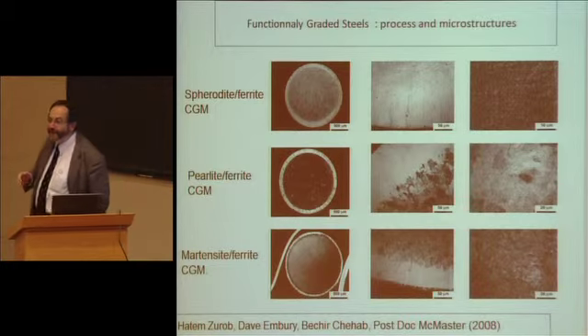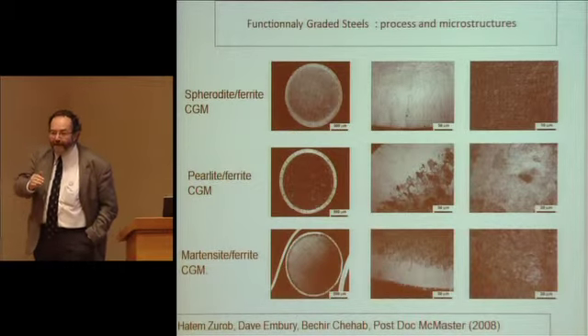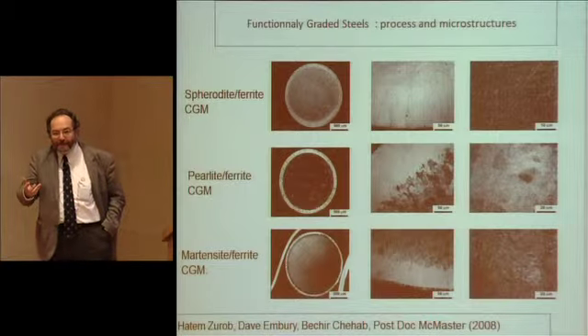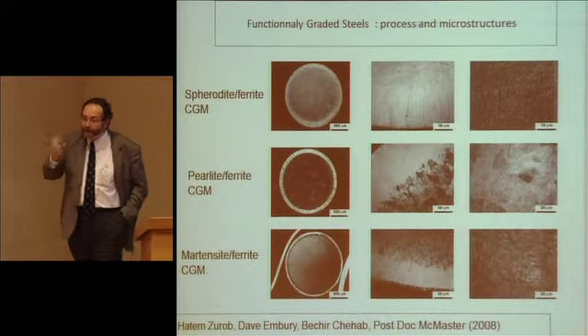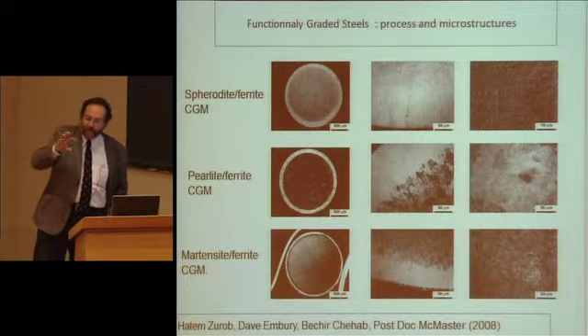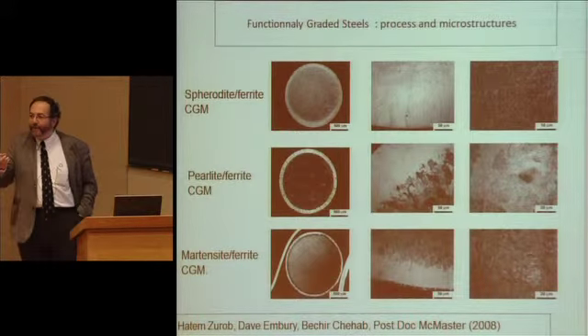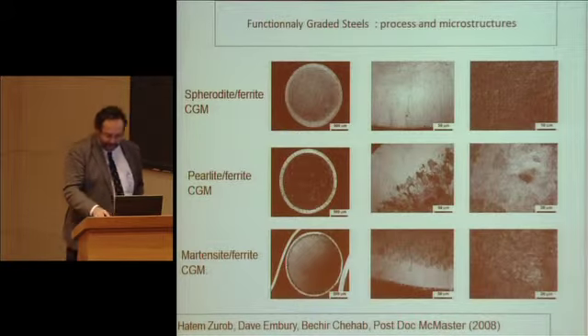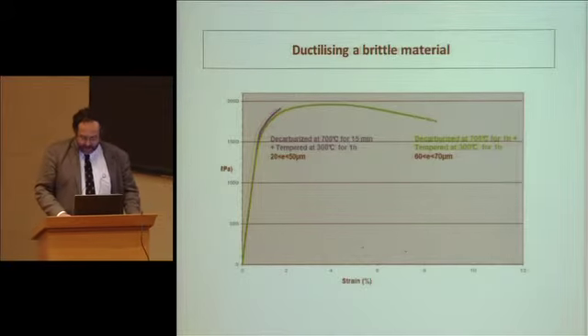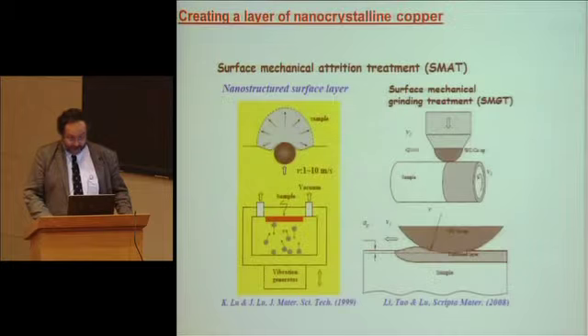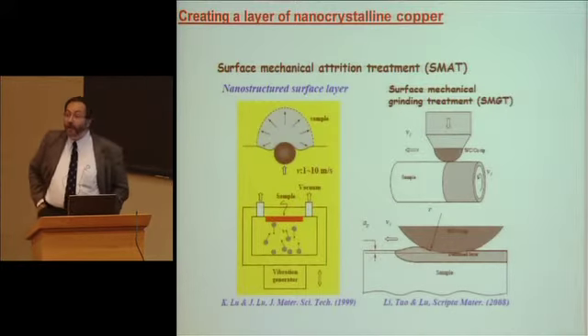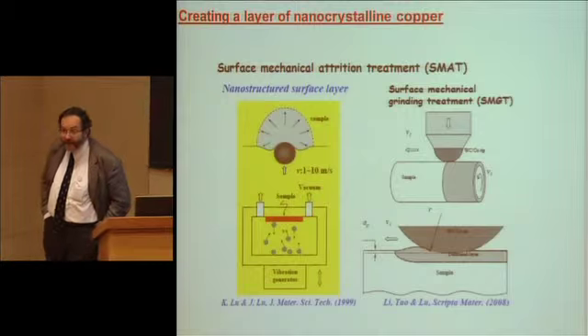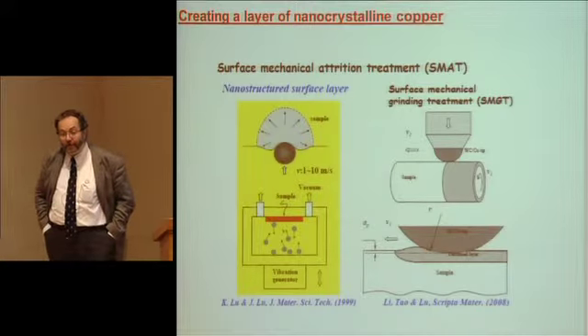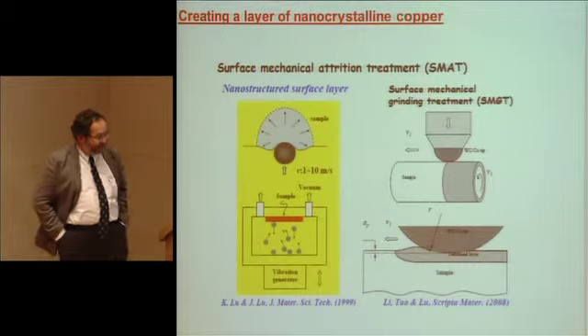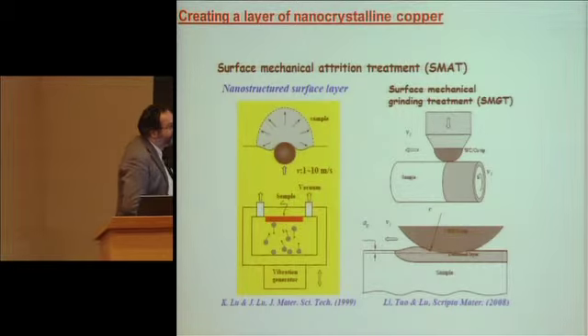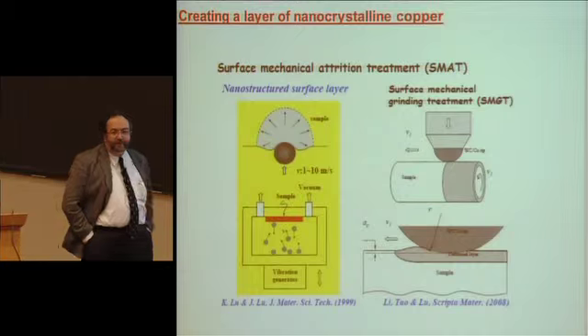What you can do is actually recarburize the outside so you can have hard, soft, hard. That would be a way of making ball bearings that are both very hard, that can withstand heavy loads because the core is hard, but that are very wear resistant or damage resistant because the crack can't propagate. So it's a way of making a fragile material more ductile. So that can be done not only in chemical terms, it can also be done in terms of microstructure. That's the trick, known as SMAT, Surface Mechanical Attrition Treatment.